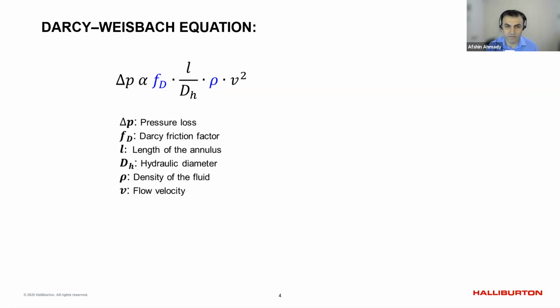You see the velocity has the highest factor here, and that's why on location, if they have losses, they bring the rate down. That means reducing the velocity, and that has a huge impact on the downhole pressure and controlling losses. But the fact is, looking at this equation, what can we change if we want to bring the downhole pressure down? Length and diameter, we cannot touch that. That is part of the well design. Velocity, yes, we can bring the velocity down, but for this specific case, that was a restriction to keep the dart running. That's why we didn't want to touch the velocity. But in general, bringing the pumping rate down is not ideal for any cementing job, because you have more tendency to end up with channeling and intermixing of the cement, spacer, and mud, and you're losing the energy of the fluid to clean the hole.